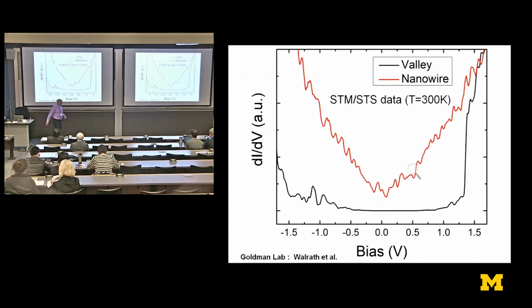One of the really nice things that came out of this work was done by Jana Waldrath, who's now graduated from Rachel's group, doing scanning tunneling microscopy, scanning tunneling spectroscopy experiments, where Jana took a wire. This is a really difficult measurement. She scanned an STM, scanning tunneling microscope tip, across the wires in the transverse direction to pick up essentially dI/dV, the slope of the IV curve, which tells you about the density of states in the material as you're scanning across.